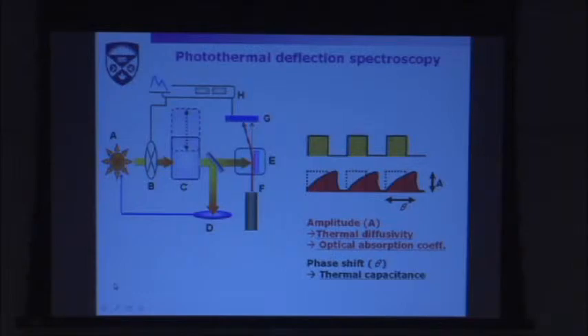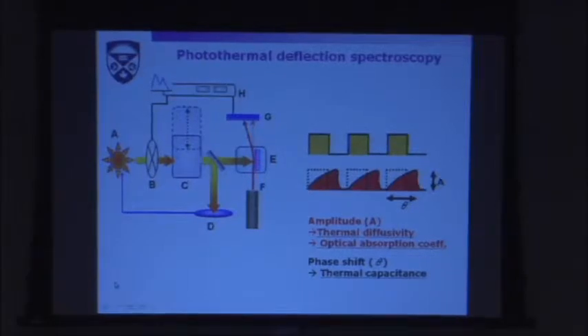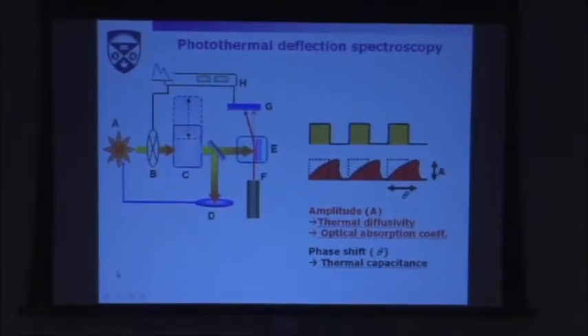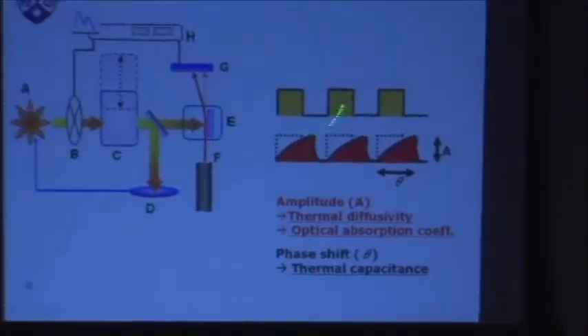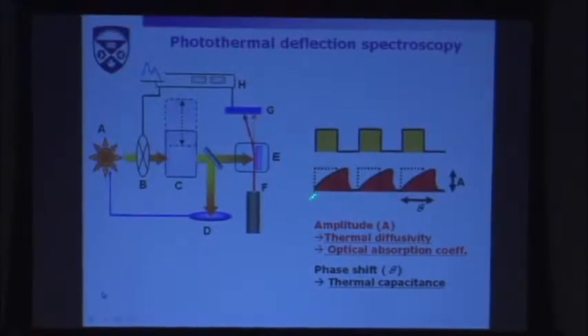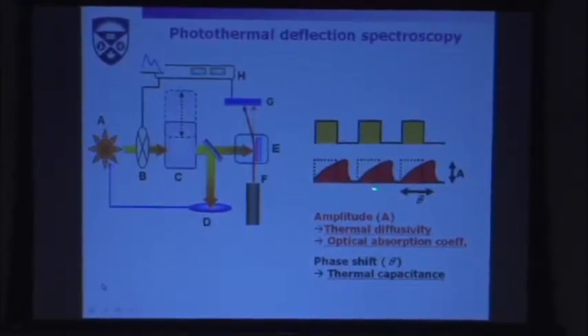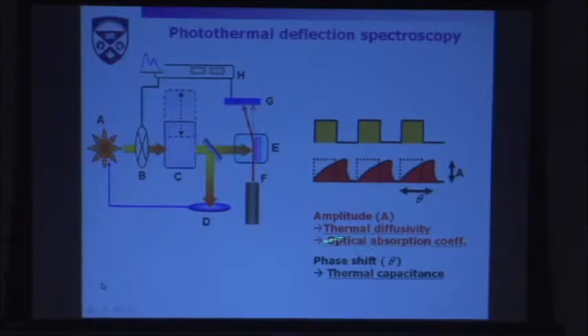Obviously, the deflection has a delay. Why? Because the sample has not an infinite thermal conductivity and not an infinite thermal capacitance. So it takes some time to heat up. So you can exploit, basically, the amplitude of this photothermal deflection spectroscopy signal. You see, this is the chopped light. This is the response, takes some time to go up and takes some time to go down, so there is a phase shift, for measuring the thermal diffusivity and the optical absorption coefficient, and the phase shift to measure the thermal capacitance of the system.